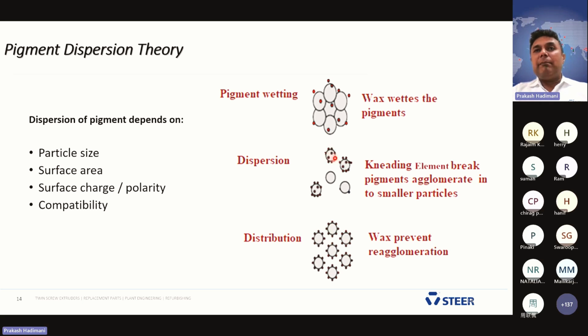Again, each pigment coated with the waxes, we call it a wetting phenomenon. This is the wax coating onto the pigment. It is called the wetting mechanism or wetting phenomenon. Once the dispersion is done, again, we are distributing each pigment, because once a pigment is coated on each particle, that pigment has to mix together with the polymer, and this has to be distributed evenly with the polymer and the pigments. We call it homogeneous mixing.